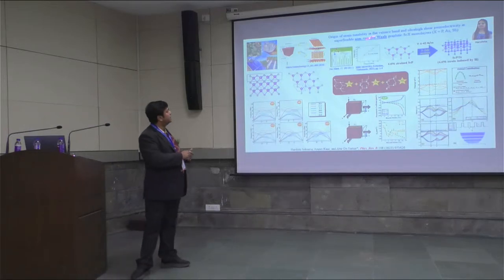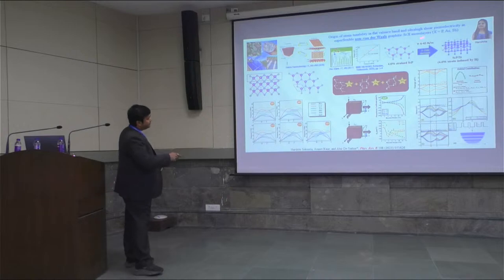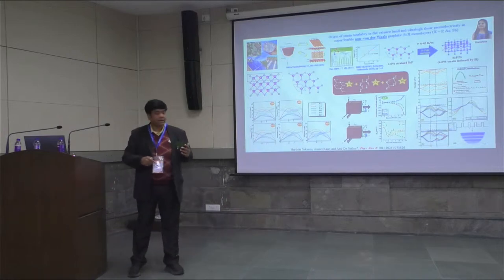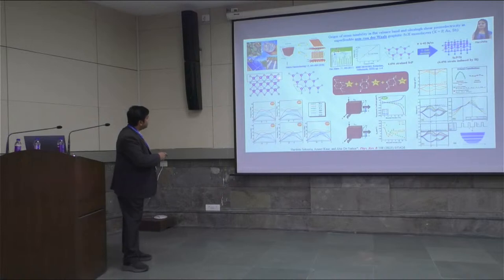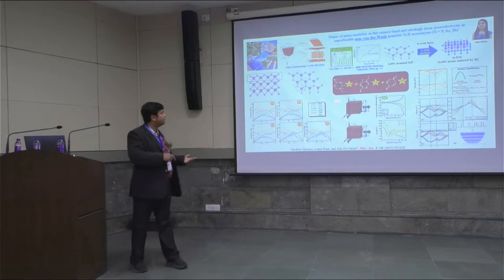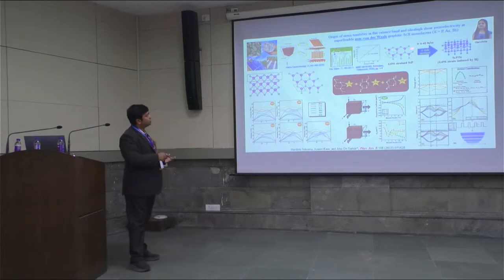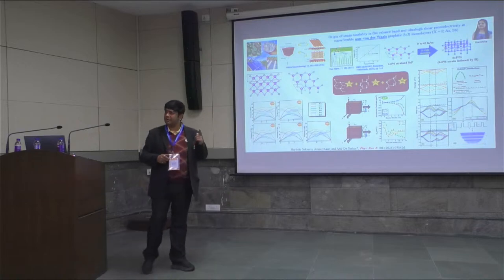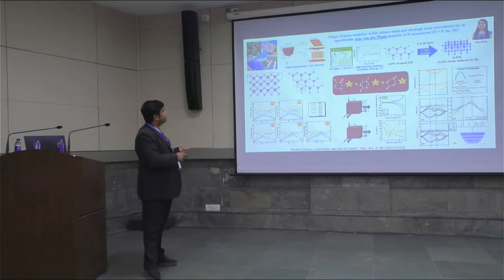So here, these scandium nitride monolayers are stable in the wurtzite phase in the bulk structure. So computationally, we have exfoliated a single layer of scandium nitride and we have optimized it. It is found to be stable and having a hexagonal honeycomb lattice structure, and it shows a very small Young's modulus, so therefore it is super flexible. And then we have explored several other properties in scandium nitride monolayers.